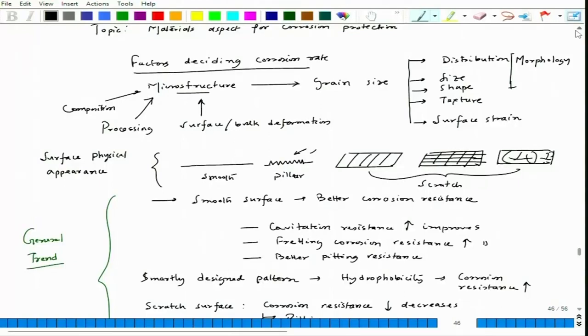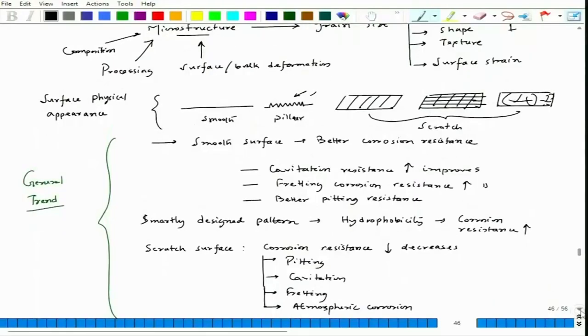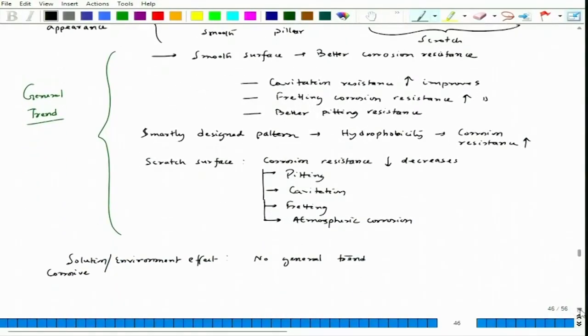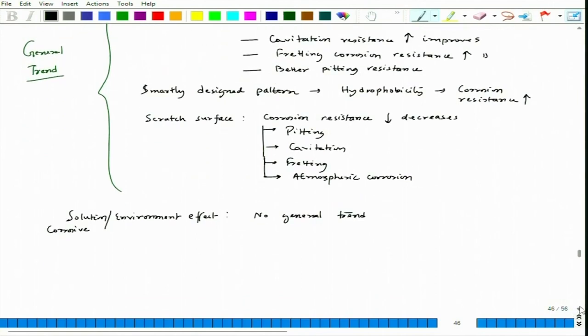Now, if we look at this entire picture, you can see that it is very difficult to draw a general trend that if we follow this route, we can have very good corrosion resistance. So, depending on the materials, the microstructure, and the distribution, we should do lab experiments to get an idea, and then follow up with a pilot plant trial if possible, and then decide the material for a particular application. So, even though it is very difficult, there are some scientific aspects.